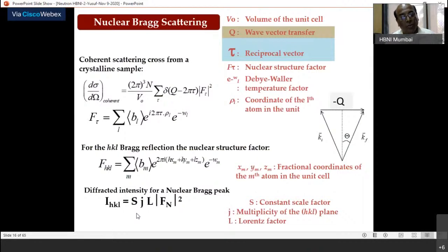Or in a given instrument, let us say we have a diffractometer at Dhruva, I can design the instrument so that I make a tighter spatial collimation. How do you do that? You put in stricter collimators, so you are cutting down the beam. Of course, you are gaining spatial resolution. You want to separate out two Bragg peaks which are closely placed.